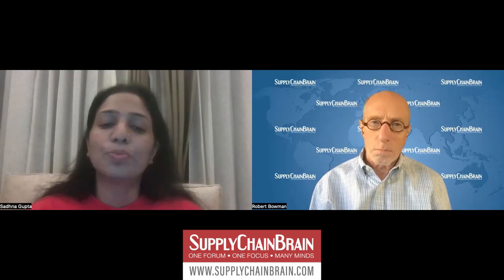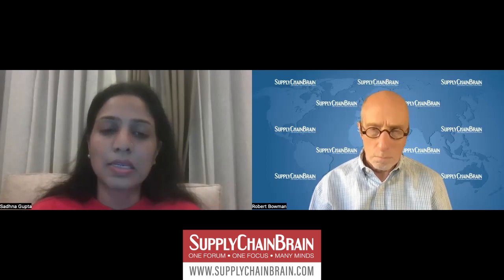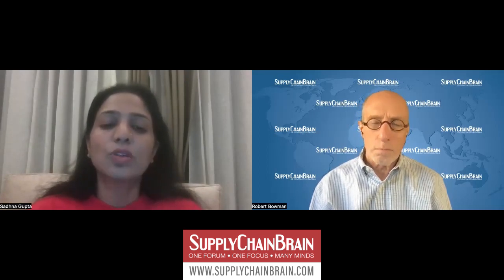This grade has multiple applications across industries like aluminum, silicones, and silanes. Around 40% of metallurgical silicon grade is used for the production of aluminum alloys, which are used in the automotive industry to make car parts like engine blocks or wheels. These parts made of aluminum alloy with silicon are stronger and lighter as compared to cast iron parts. Then 36 to 38% of silicon metal is used to manufacture silicones or silanes, which are used as insulating material in the construction industry. It is used as a sealant or adhesive.